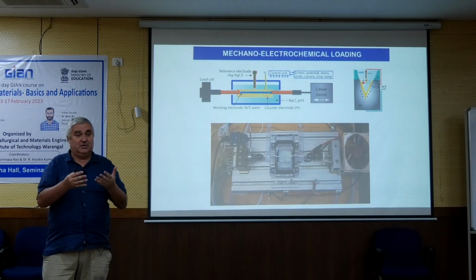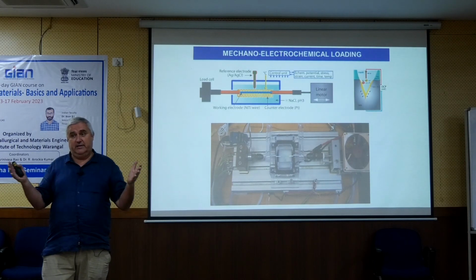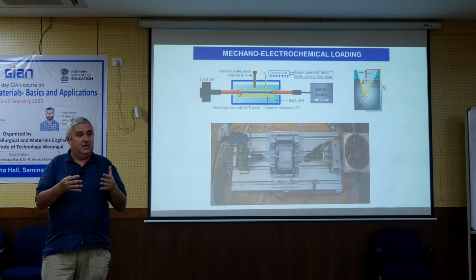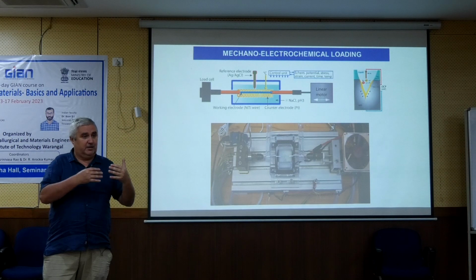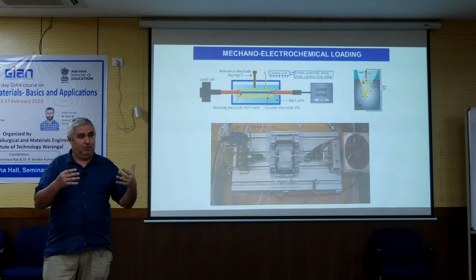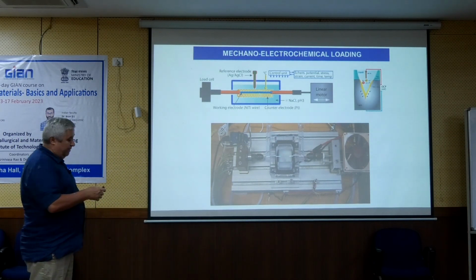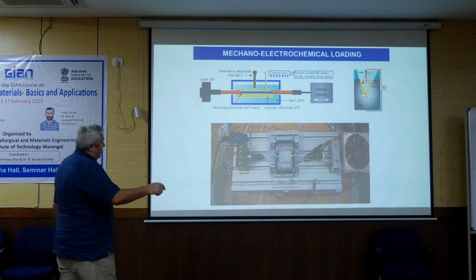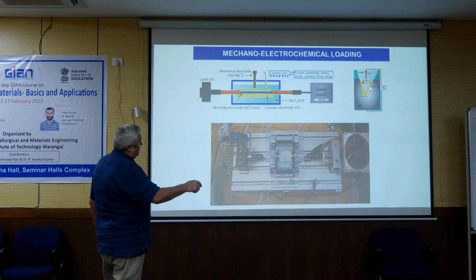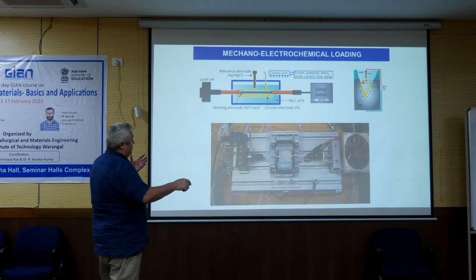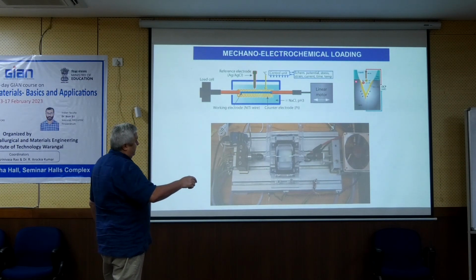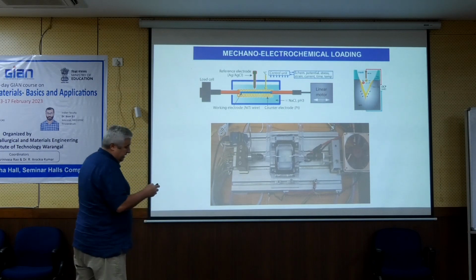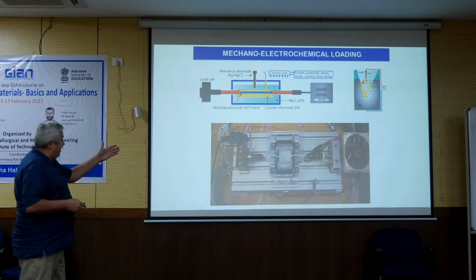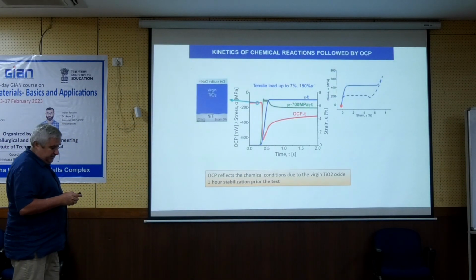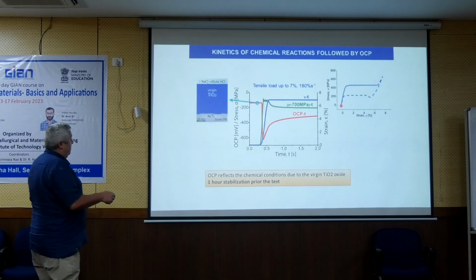So the corrosion process in fluid is much faster. It's the same philosophy as a corrosion test which is performed on metal, but here it is performed dynamically. And the product of this reaction is this yellow, it's like a gel, and it covers the surface of the crack. So we have this experiment, and now this is what we measure.